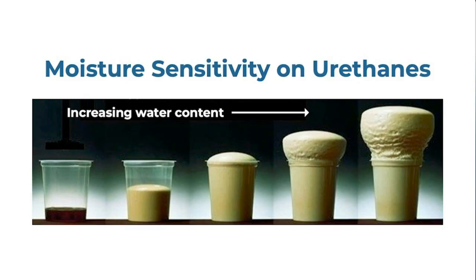In this slide, we're going to talk about moisture sensitivity of urethanes. Urethane components are moisture sensitive and will react with atmospheric moisture. Protecting the urethane component is simple and only requires an inert gas blanket on the A and B components. This graphic shows how increasing levels of water can cause foaming. Urethane potting compounds are elastomers, not foams. When a urethane is contaminated with moisture, it becomes a foam, and we want to protect it so that it doesn't become a foam in your potting application.